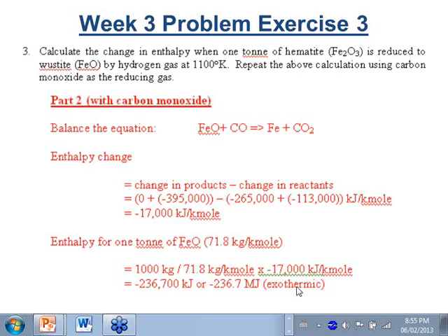And it's an exothermic reaction. So by doing reduction with carbon monoxide of wustite to metallic iron, you actually are giving heat off to the process, which is a good thing. So there are 2 ways of how iron ore or wustite can get reduced: by means of hydrogen reducing gas or by means of carbon monoxide. One of them is endothermic in the case of hydrogen, and the other is exothermic for the case of carbon monoxide.